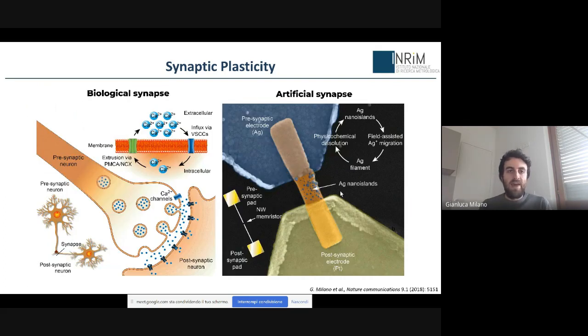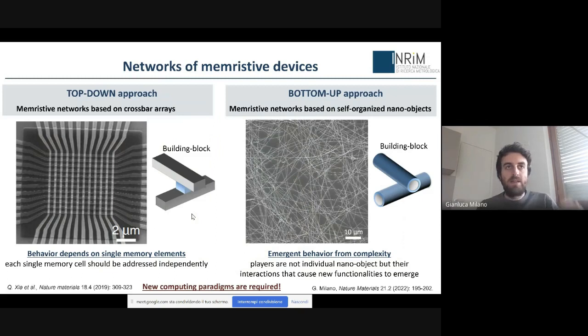And so basically, this is what we have done in this paper, in collaboration with the Jülich Research Center. We can emulate the influx and extrusion of calcium ions by using the migration of silver ions on nanowires that act as memristive devices. So these are silver nano-islands of a few nanometers on the surface of zinc oxide nanowires that emulate the extrusion and influx of calcium ions and can give rise to the main features of biological synapses that I showed before. So these are basically two-terminal devices, exactly like biological synapses. But anyway, this is only a single synapse.